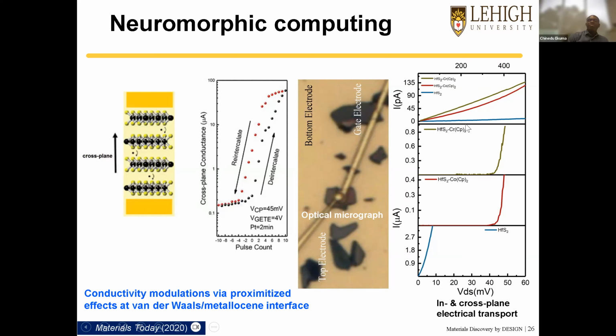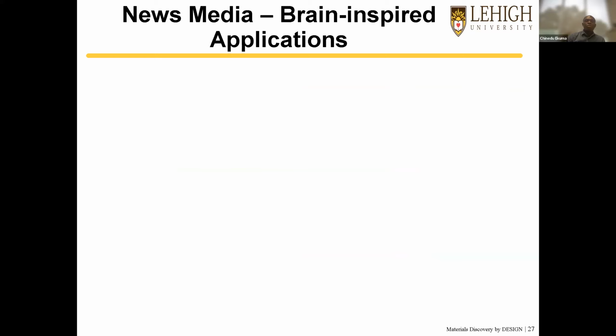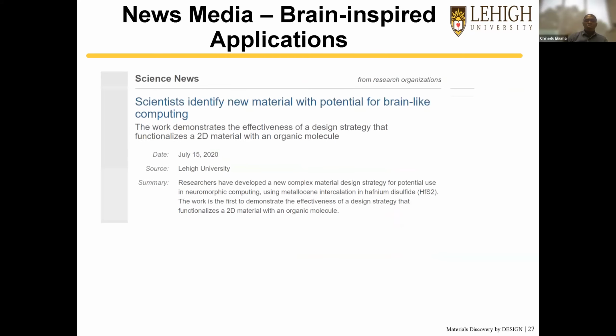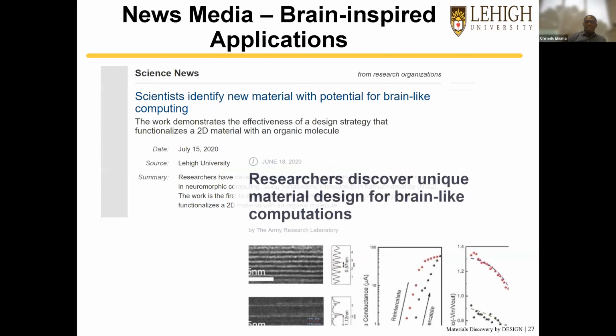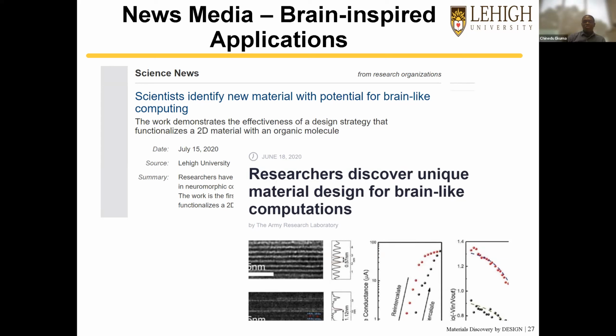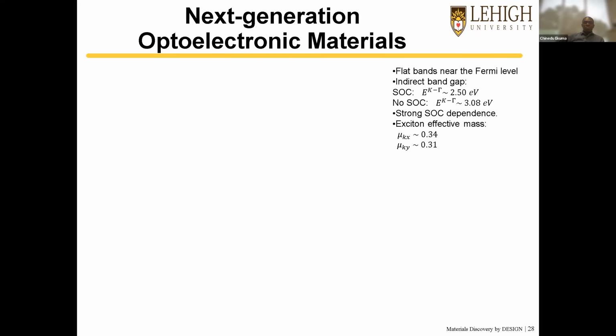But the most important observation in this material is the enhancement of this cross-planar transport by almost 400-fold, as you can see here. And this is a signature of dynamical reconfigurability, which is well sought after for neuromorphic application. So that is why we tag this system as a material for brain-like application. And this was covered by various scientific media when we first published this in Materials Today. Just to add, I think we are the first group to show the intercalation of molecules in 2D van der Waals systems. So hopefully it becomes a research niche where others could start looking at some of these problems.